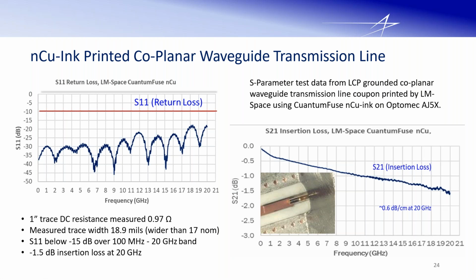I would say the nano copper gives us comparable results to that, about minus 1.5 dB type of loss at 20 gigahertz. That's good as a reference. If this was foil copper, etched foil copper, we would probably be up here between 0.5 and 1 dB. So it's not as good as foil copper, but certainly well enough for what we want to do, and it kind of drives home the reason why we're using a hybrid approach.